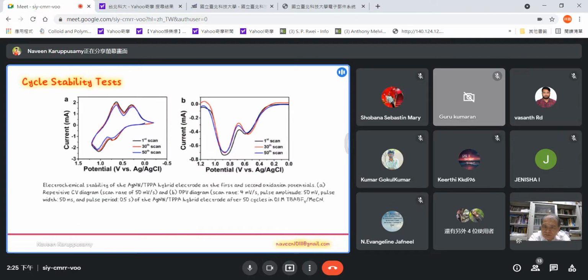Then the cyclic stability test. They performed up to 50 scans. After the 50 scans, there is a slight change in the oxidation, anodic and cathodic peak current. From this, we can clearly observe the ability of the passivation layer.